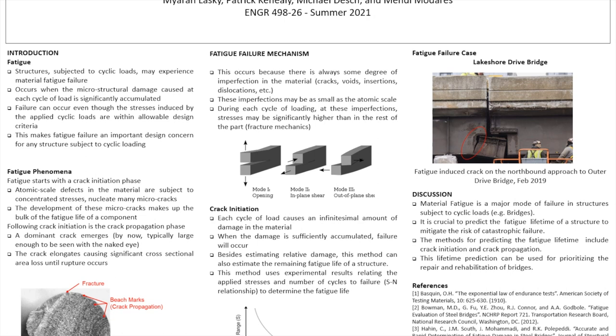Many microcracks form and develop over a comparatively longer period of time than crack propagation. When a dominant crack forms, we have moved from the crack initiation phase to the crack propagation phase. This crack elongates until sufficient cross-sectional area loss occurs, resulting in rupture. Compared to initiation, propagation is considerably shorter.